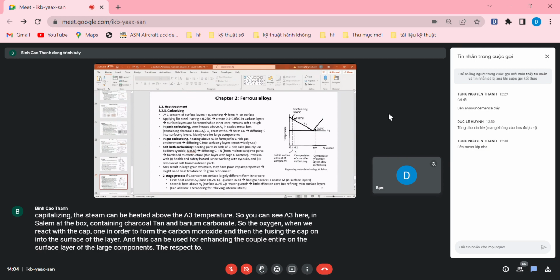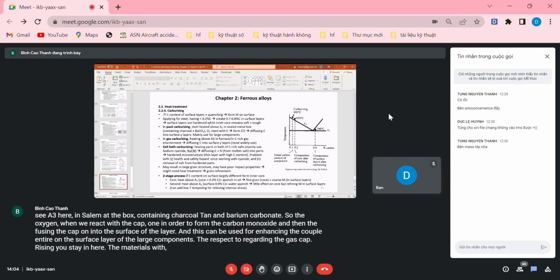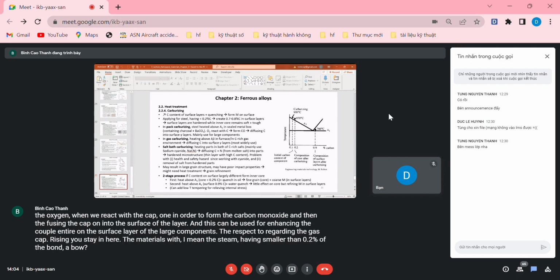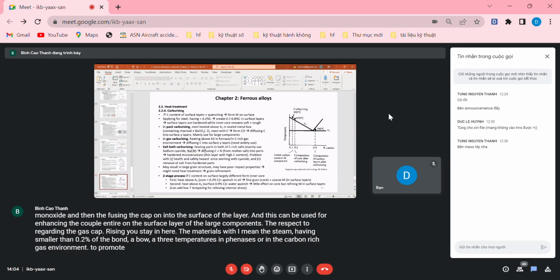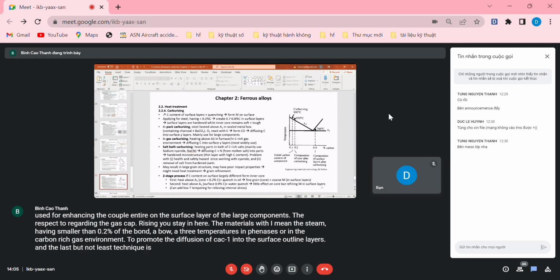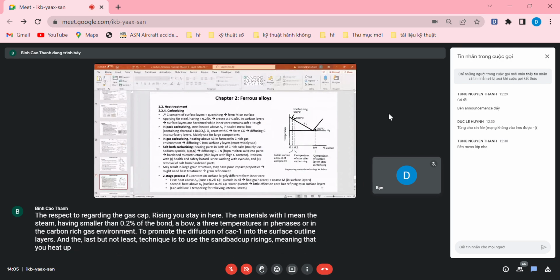With regard to gas carburizing, you heat up the steel having smaller than 0.2% carbon above the A3 temperature in furnaces or in a carbon-rich gas environment to promote the diffusion of carbon into the surface austenite layers. The last but not least technique is salt bath carburizing, meaning that you heat up the part in a bath of carbon-rich salts.